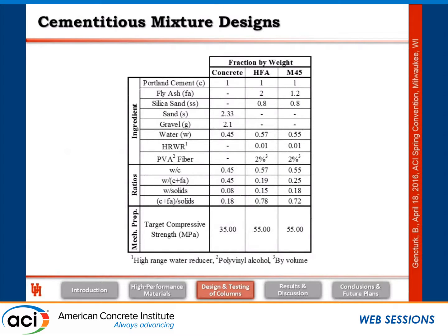This is the conventional concrete with a target strength of 35 MPa. And then we had 2 ECC designs. These are very common designs from literature. The only difference between the 2 designs is the amount of fly ash. This has twice the amount of fly ash. This one has 1.2 times the amount of fly ash. And they both have 2% by volume of PVA, polyvinyl alcohol fibers, in the mixture.